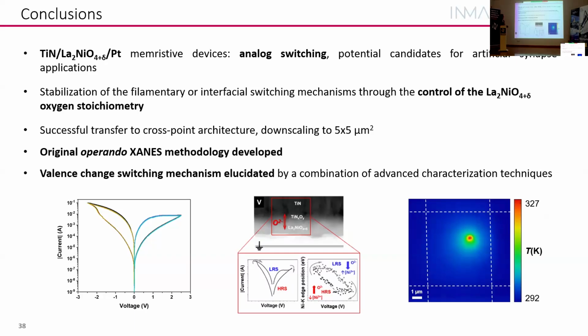So just as a summary, take-home messages, we optimized very nice titanium nitride, lanthanum nickelate, platinum memristive devices with quite good performance metrics and analogous switching. We could control the different types of switching by changing the oxygen stoichiometry. We could transfer to cross-point architecture. Then we've done lots of characterization, but one original operando XANES methodology to really measure these changes. And we elucidated the mechanism of the switching by combining all this.